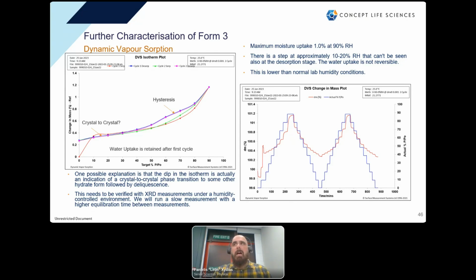You could see the creation of a new hydrate, followed by a deliquescence step. On the desorption step, there is a hysteresis, and when the first cycle closes, it's not reversible. But the second cycle follows practically the system without that small step at 10 to 20% relative humidity.